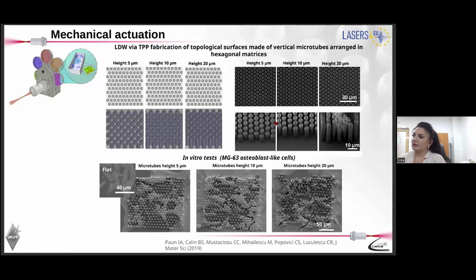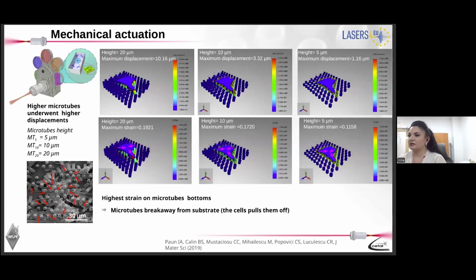These are the scanning electron micrographs of the 3D structures that we made, the microtubes with different heights. And here is an in vitro test with osteoblast-like cells seeded on these microtubes. You can see already here that we have a different behavior as a function of the microtube's height. As the microtube's height increases, we have much stronger deformations because the osteoblasts are acting with some traction forces here.